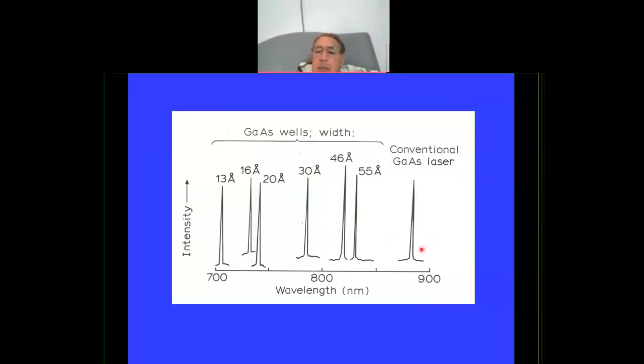So you can see here by changing the quantum well size. For example, a very large quantum well, 55 angstrom, 46, and so on. You can see I can tune the laser from 700 nanometers to 900 nanometers by changing only one parameter, not the material, but just the quantum well size. So you can see from 13 angstrom to maybe 55 angstrom. But look here what is very important. By changing the quantum well by only 3 angstrom, you can change this emission quite largely.